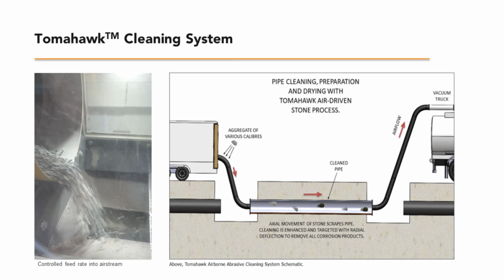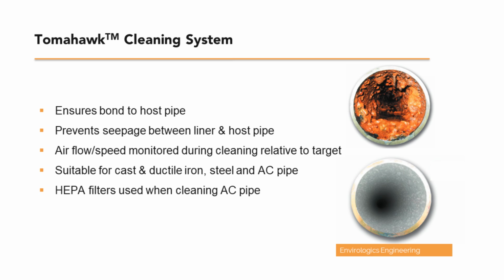The system uses an auger to control the feed rate of the stone, as well as to control the airflow in the pipe to adjust the intensity of the cleaning. The end result is a bare metal pipe wall, assuring a strong bond between the liner and the host pipe. Monitoring airflow and speed relative to benchmarks for a clean pipe helps determine when cleaning is complete. The process is suitable for cast and ductile pipe, steel pipe, and asbestos cement pipe.